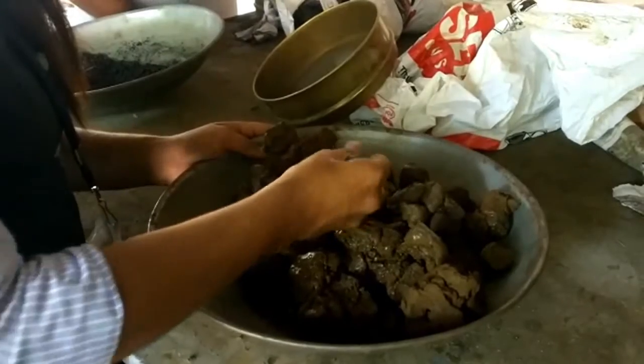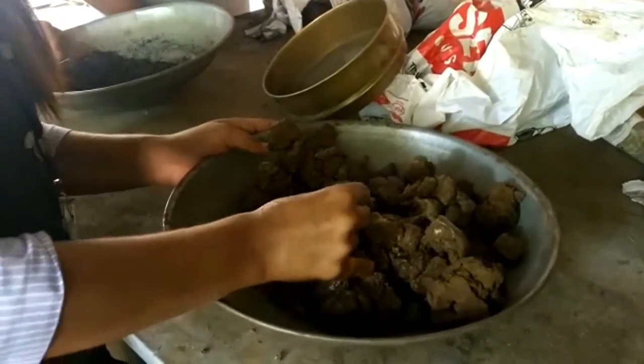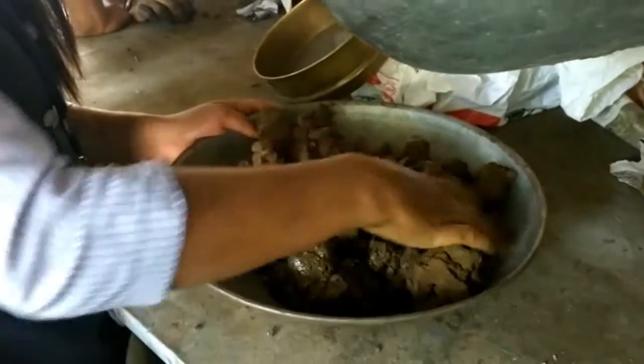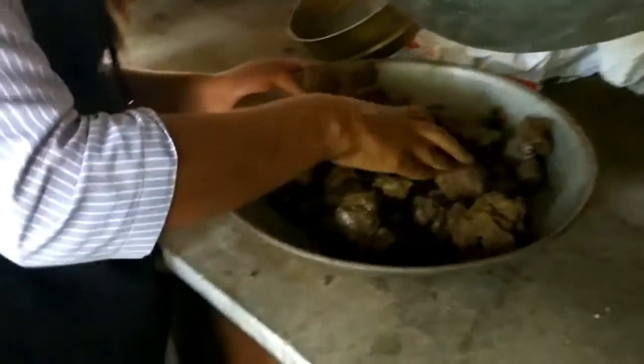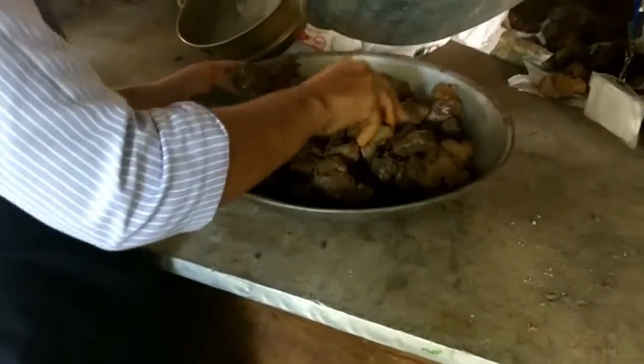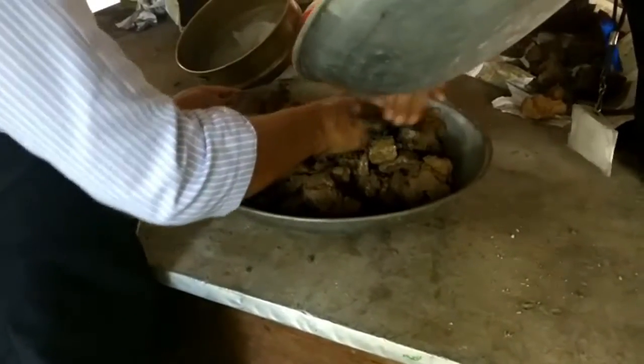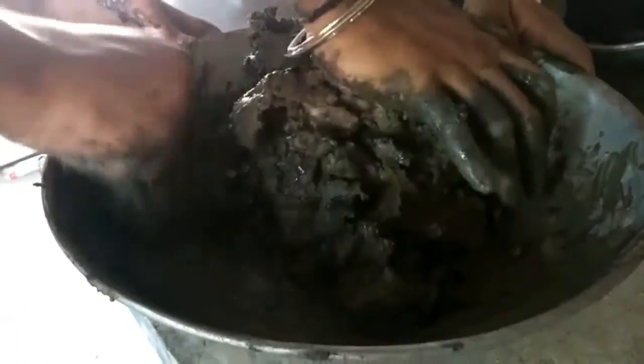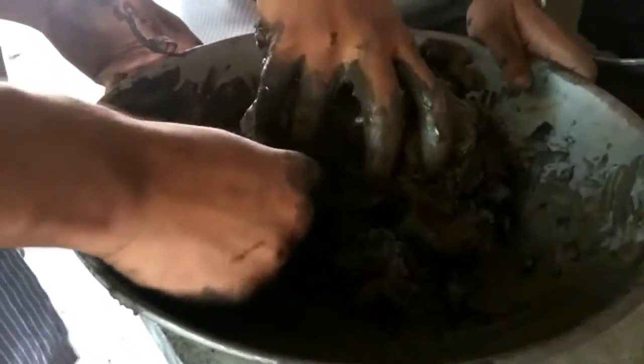Here we have developed a brick by adding our material into it. First, we took 4000 grams of clay and added water and Coal Washery Rejects of 20% weight of that of clay, and mixed it thoroughly to form an even mixture.